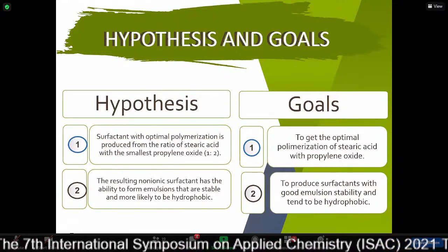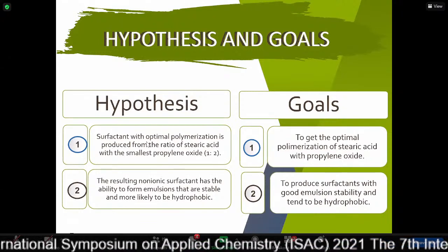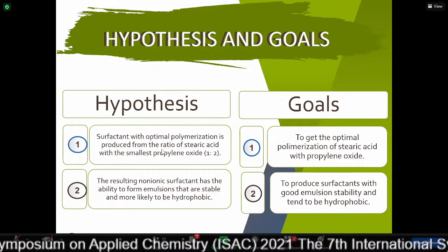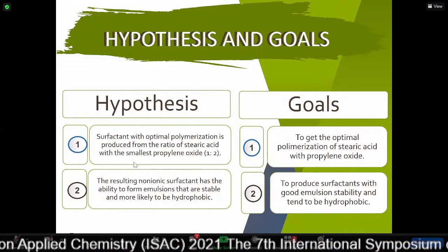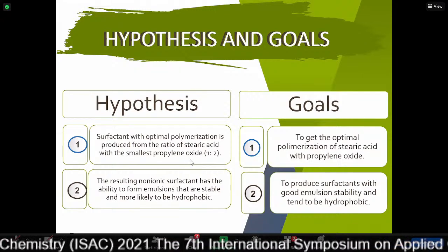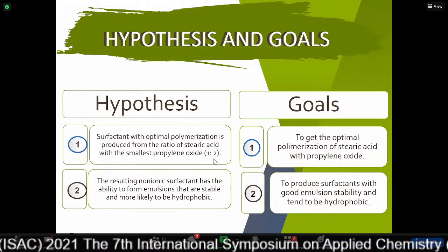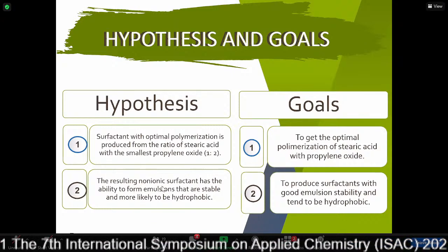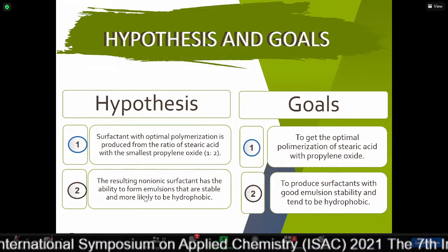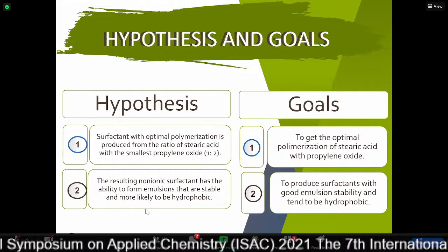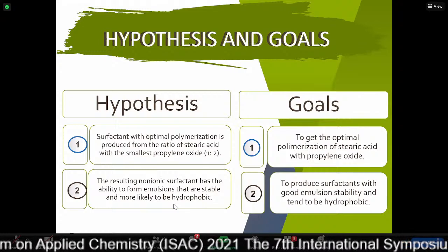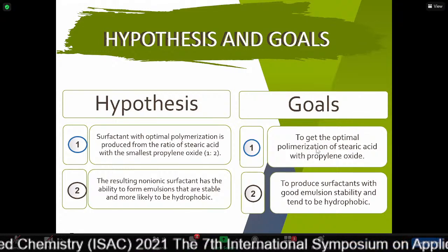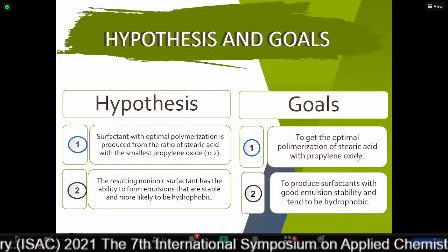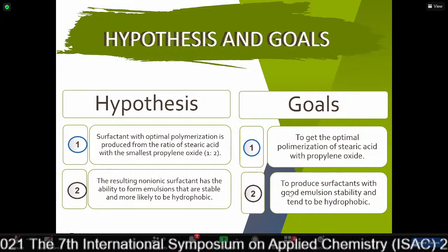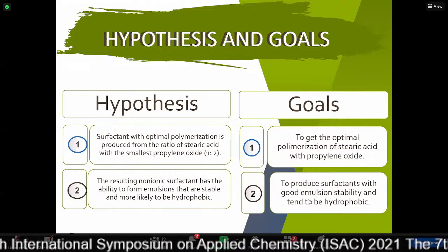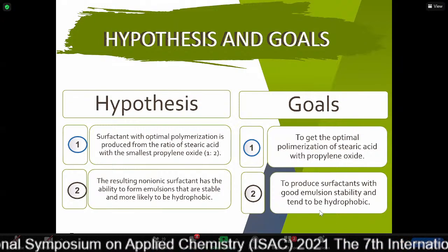This is for the hypothesis and the goal. The hypothesis is, first, surfactant with optimal polymerization is produced from the ratio of stearic acid with propylene oxide, which will be included, of 1:2. And then the resulting non-ionic surfactant has the ability to form emulsions that are stable and more likely to be hydrophobic. So the aim of this work is to get the optimal polymerization of stearic acid with propylene oxide, and then to produce surfactant with good emulsion stability that tends to be hydrophobic.